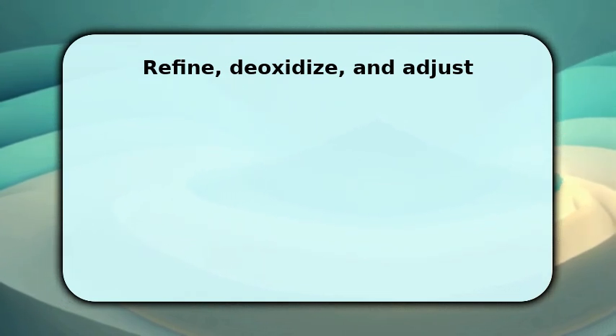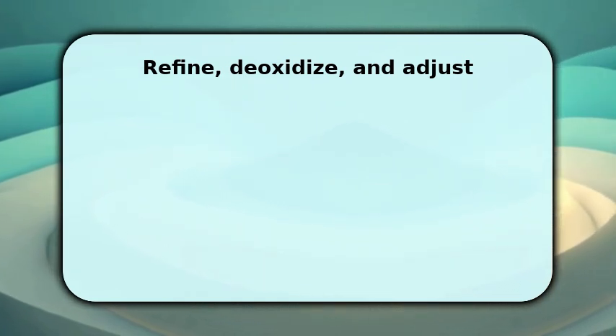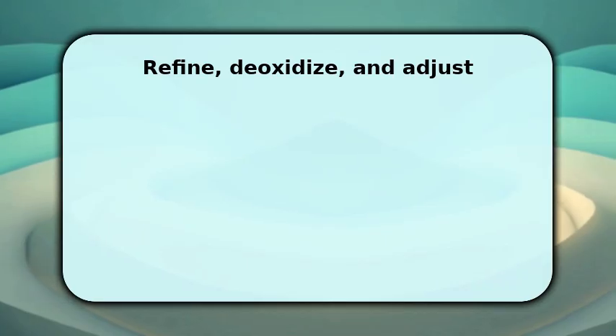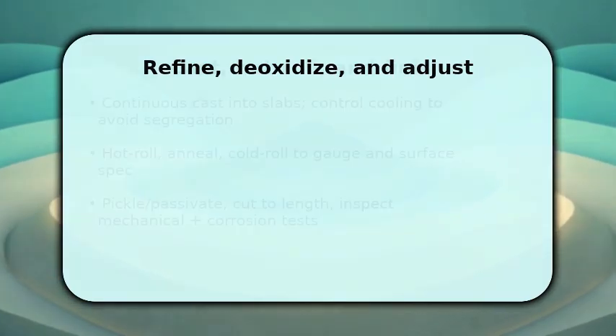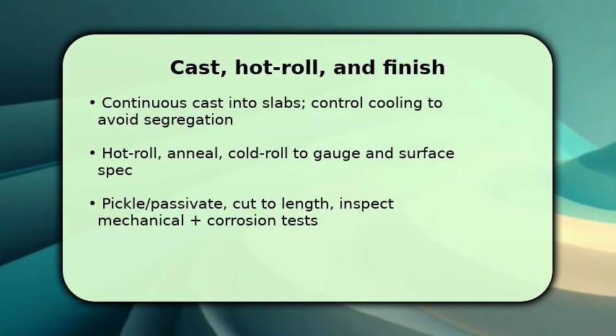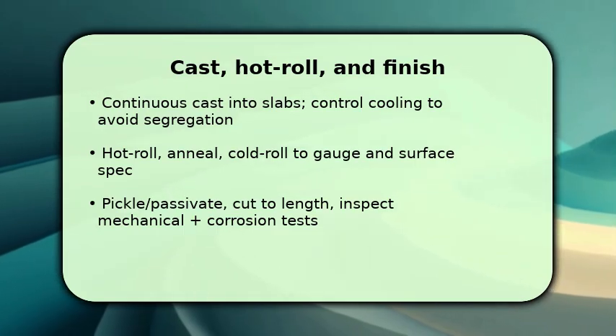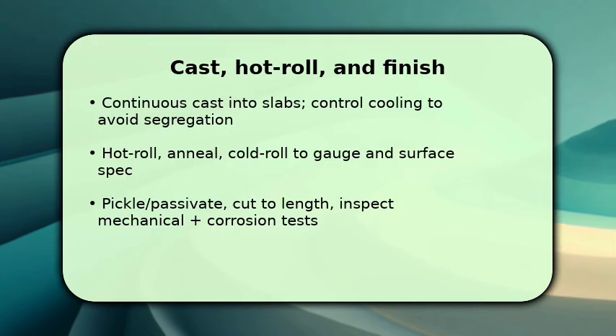You cast the refined melt into billets or slabs using continuous casting, controlling cooling rates to prevent segregation. Once solidified, hot roll to break down structure, then anneal and cold roll to final thickness while monitoring grain structure